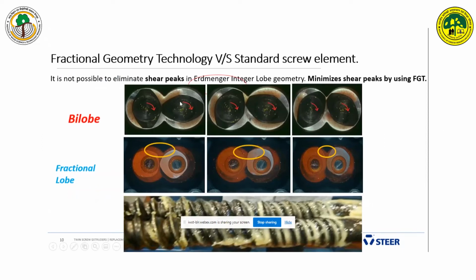This is the difference between bilobe technology and fractional geometry technology. At the top, you have bilobe technology and fractional geometry technology. In bilobe technology, I have already explained the peak shear. The melt is trapped in the narrow gap and degrades the polymer. But in the case of fractional geometry technology, it maintains the melt, and there is no degradation, no peak shear. If you see, when the screw starts rotating, it has full melt between screw to screw. There is not much degradation. It is a uniform shear. This picture was taken from the extruder. We see the input material is white and the output is also white. There is no degradation, no yellow coloration in fractional geometry technology.